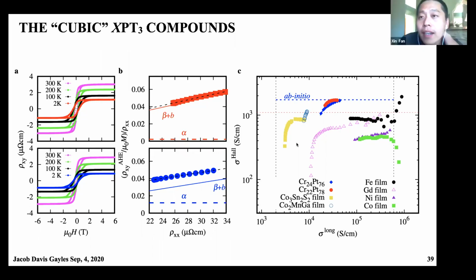Yeah. Right. I mean, this is for the spin Hall effect, right? You have for platinum the largest, but if you go higher in spin orbit coupling, it doesn't increase your spin Hall effect. Right. But have you calculated the spin Hall effect rather than the anomalous Hall effect, or the spin anomalous Hall effect? The spin Hall effect on a magnetic material, you mean? Yes. So if I want to use this particular material as a spin current source, I have not calculated the spin Hall effect. I could possibly do that though.